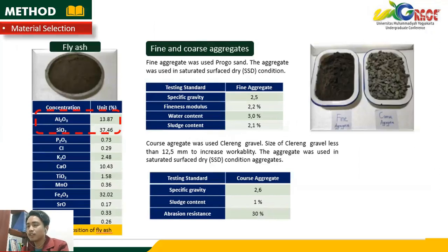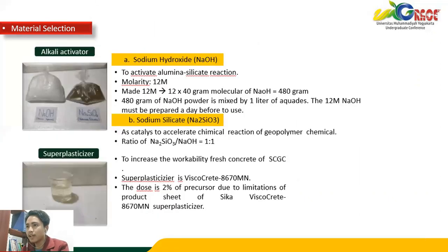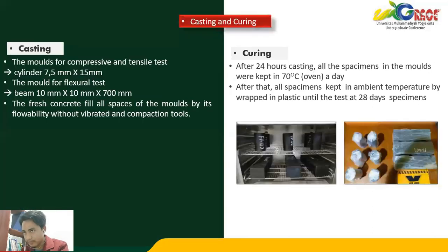And this is the method. The first one, material selection. We use local material for our experiment. The first is fly ash, which contains alumina and silica, and fine and coarse aggregate. For fine aggregate we used Progo sand, and for coarse aggregate we used Clereng gravel. And this is the alkali activator. We use sodium hydroxide and sodium silicate to activate the alumina silica reaction, and the superplasticizer to increase the workability of fresh concrete of SCGC.